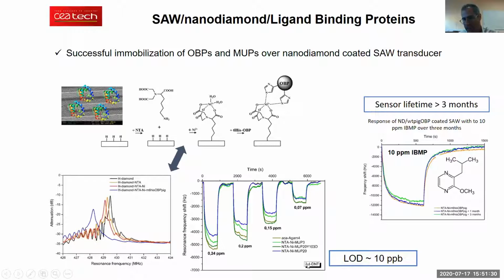We also looked at the stability of the sensors, and here I'm just showing an example of response. This is a sensor that was functionalized with wild type pig OBP, and we exposed it to 10 ppm IBMP on the first day of preparation, and then after 1 month and 3 months. You can see that the response is very much the same after 3 months of storage in fairly standard conditions.